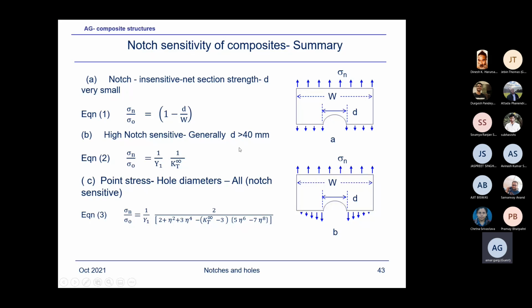The other extreme is highly notch sensitive, and we will discuss the implications. If I remove this Y, you would recognize Y is just a finite width correction factor, so forget about this one. Suppose sigma n by sigma naught equals 1 upon kT, like an isotropic material, where you want to predict the elastic residual strength without considering plasticity, then the strength would be 1 upon kT. Suppose kT is 3, then 1 upon 3 would be the residual strength ratio.